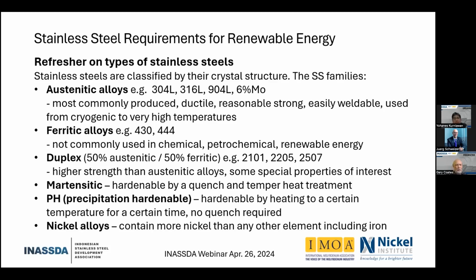Heat it up to a certain temperature, you quench it in oil, for example, and you can get a very hard and very strong material. Or the precipitation hardenable ones, which are hardenable by a different mechanism, a precipitation mechanism, where they're heated up to a certain temperature for a certain length of time so that the precipitates form, and then they don't need a quench after. And they have some special applications where you want to avoid distortion, which may come from that rapid quench of the martensitic types.